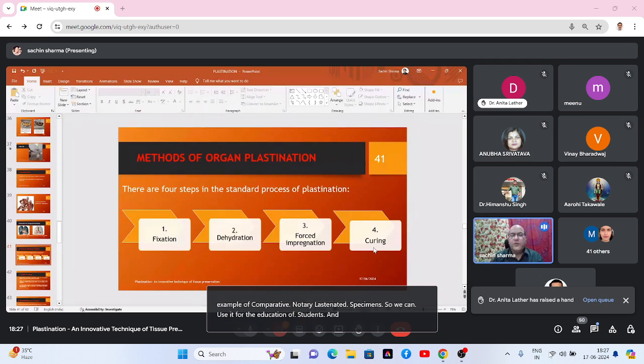Now the method of organ plastination. Again, these are the 4 steps: fixation with formaldehyde or formalin, dehydration with acetone, impregnation with resin, and curing with gas. Fixation will take 1 to 2 days. We will use 10% formaldehyde solution for fixation. A minimum fixation approach using a low percentage of formalin and a short duration can produce a more flexible and natural looking specimen.